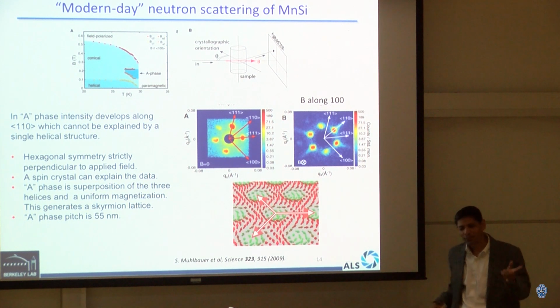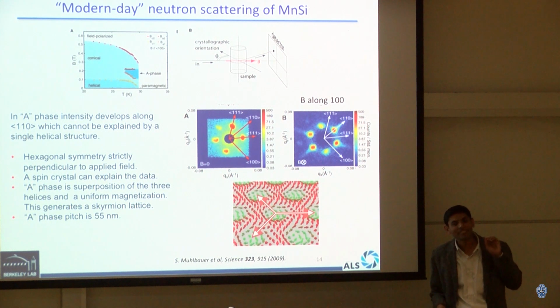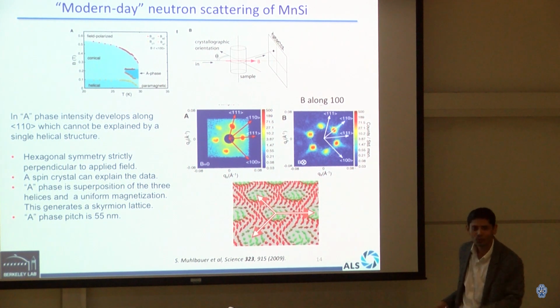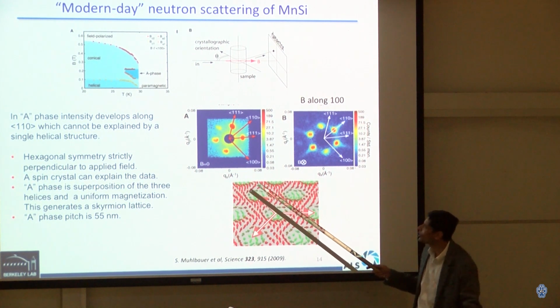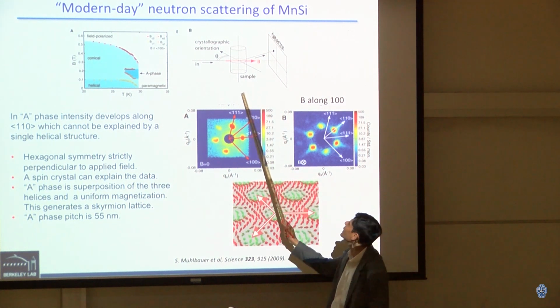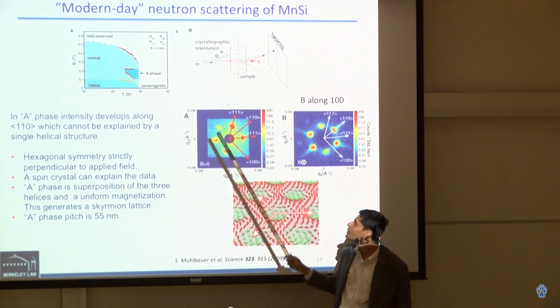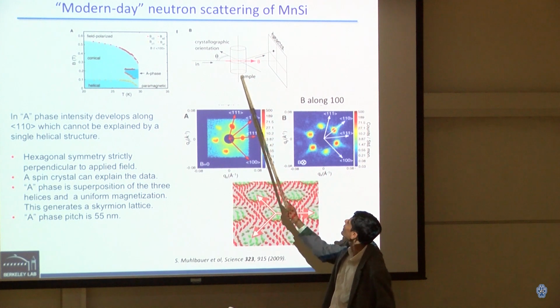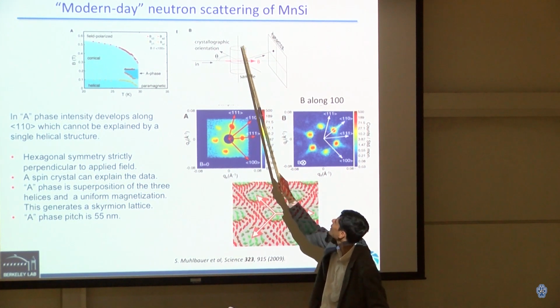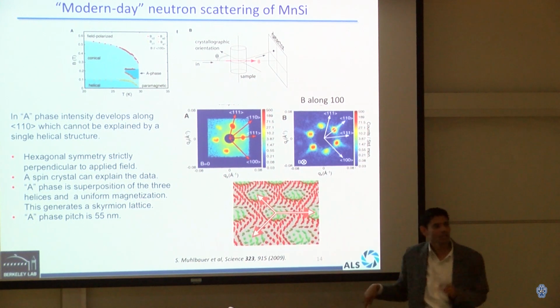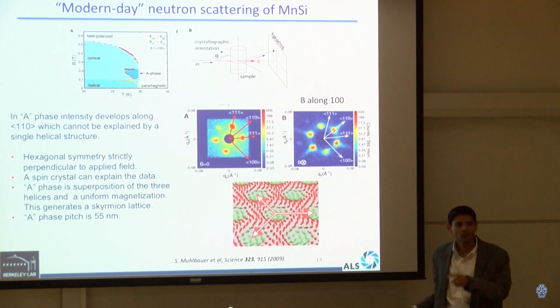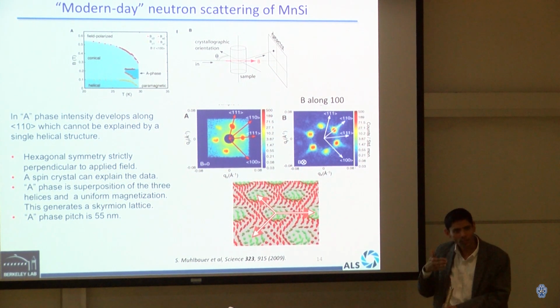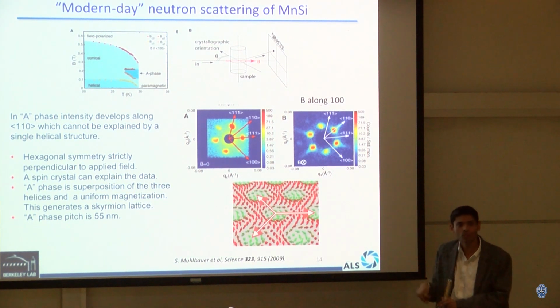And I think you brought a very important point. So the manganese silicide people have been studying it since 1960, right? Nobody could find this thing. That's because everybody was applying the field in this direction. You see the crystal, this is the sample, and the beam comes in and they scatter, and everybody was applying the field in this direction. Mühlbauer and Pfleiderer are the only ones who figured, wait a minute, if it's a skyrmion, then it should happen in the plane perpendicular to the film.